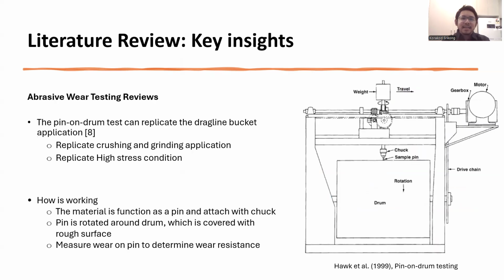For abrasive wear testing, this literature shows that the pin-on-drum test can replicate the dragline bucket application. The concept of this testing is shown in the right picture here. The tool material functions as a pin, and the pin rotates around the drum, which is covered with a rough surface. So the wear can be directly measured by the loss of material on the pin.